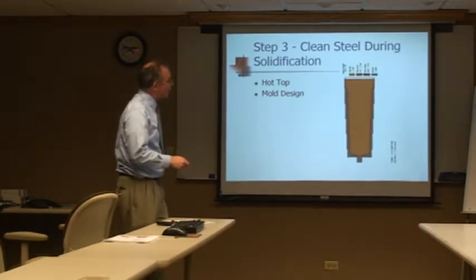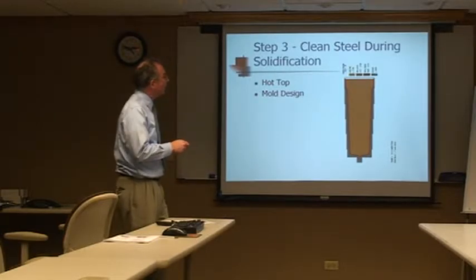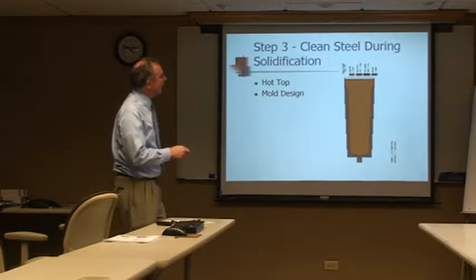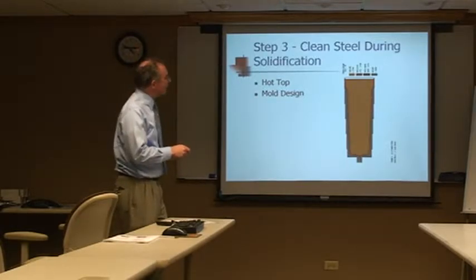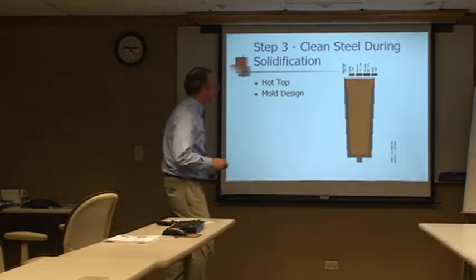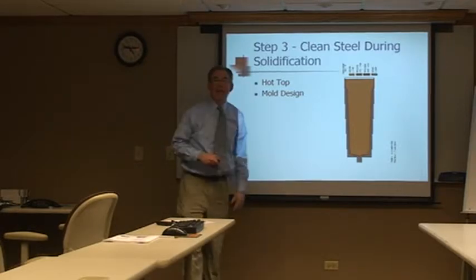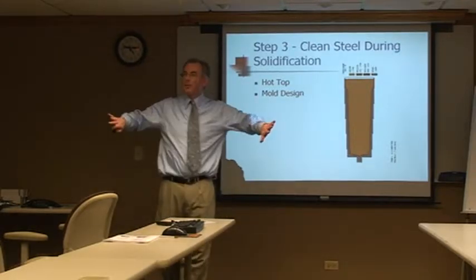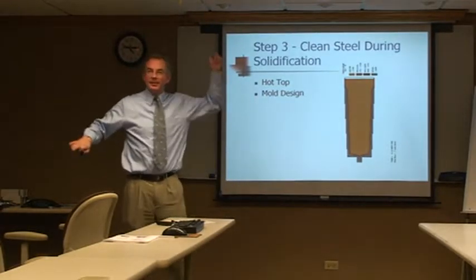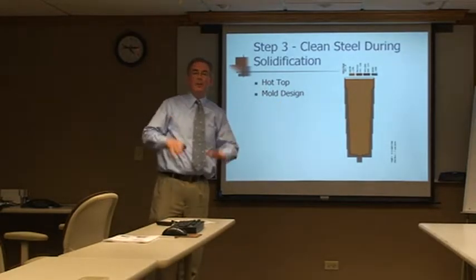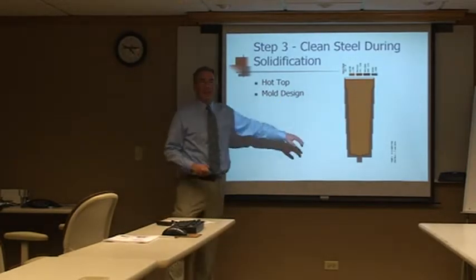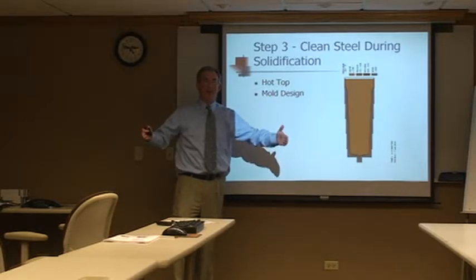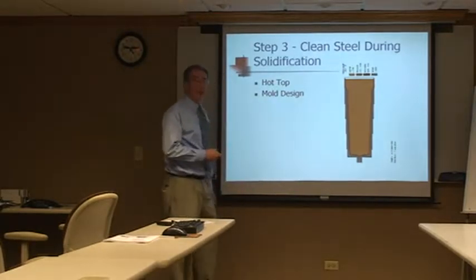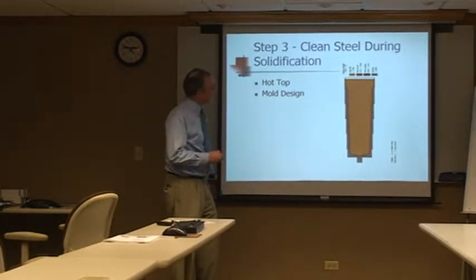If you look outside here, you have this gray shell right here. Then inside, you have this red line. That's the solidification front right there. That's the liquid solidifying. So the first thing that happens is the steel comes in, it hits the mold wall, and it chills. So what does that create? It's going to create a chill skin. And then from there, we're going to begin to solidify.